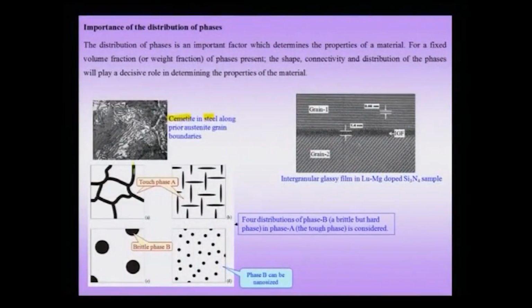Therefore, the region which is shown by black, which is right here, is my hard and brittle phase, which as you can see has multiple morphologies as in the 4 schematics shown. Therefore, when I am talking about distribution of phases, I need to know the shape of this phase B, the way it is present. When I am talking about shape, it could be needle like as in this case, which is typically the morphology observed in many cases. It could be spherical, it could be cylindrical, it could be irregular, it could be feather like, etc.